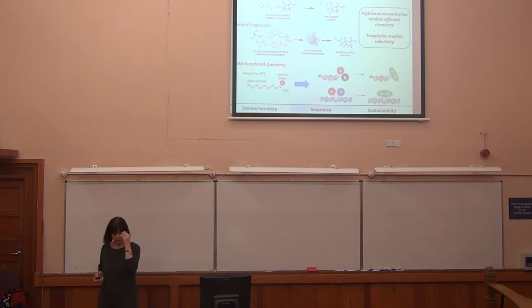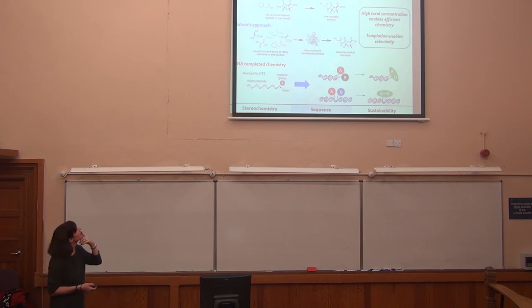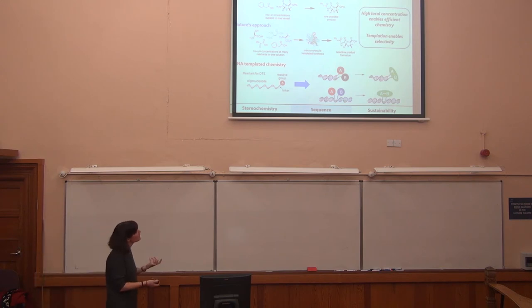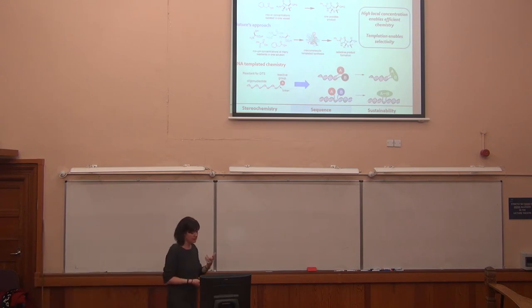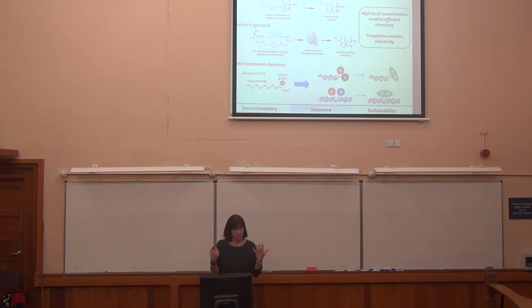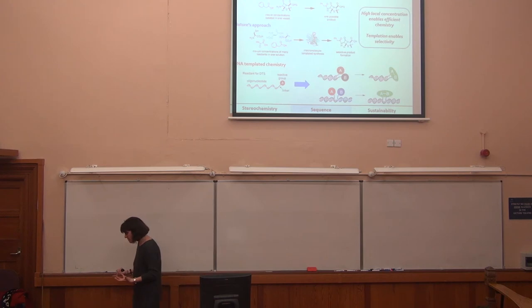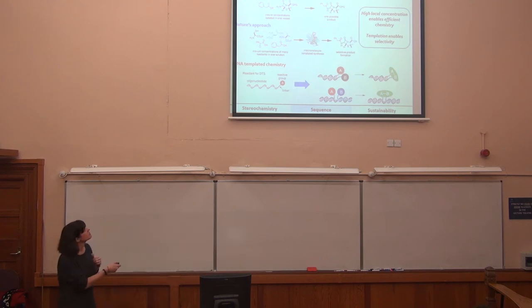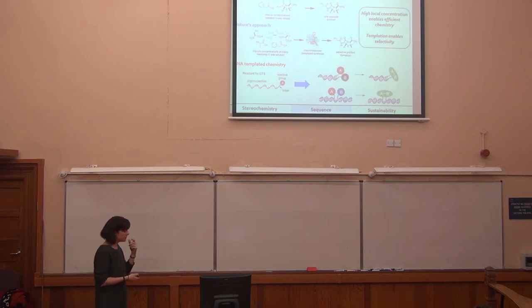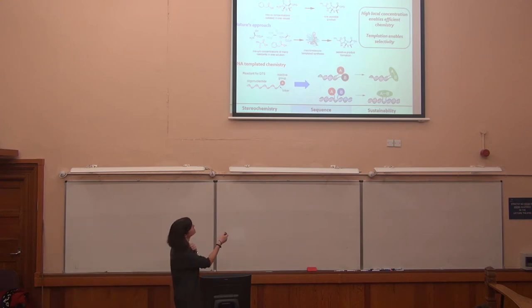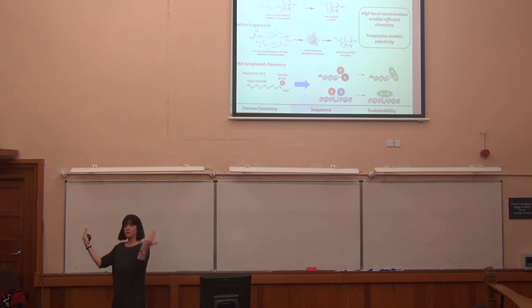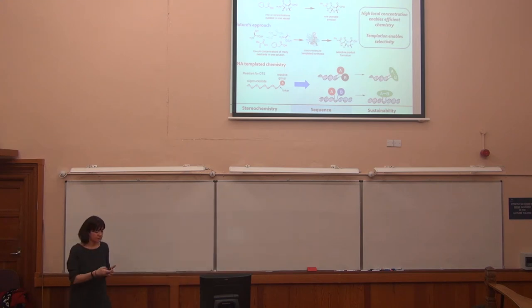And as I said, when we started this program, I was trying to work it out, maybe close to 10 years ago, with Andrew Turpin's group, where we were quite interested in how we could look at some DNA templated chemistries to access sequence control materials. And David Liu at Harvard is very much a pioneer in this area, and has shown really nicely that, as I said, if you take an oligonucleotide with a linked reactive group, you can use hybridization reactions to either bring things to an end of helix, or across a nick architecture, allow two reactive groups to come into close proximity and allow them to react.